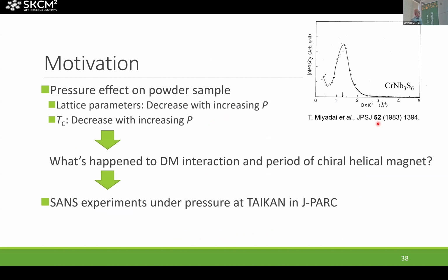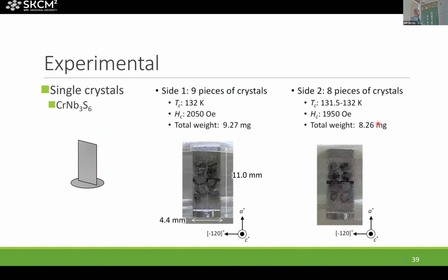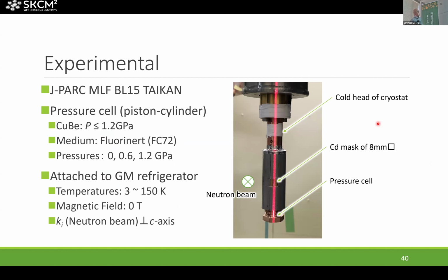So we have performed an experiment under pressure at J-PARC using a single crystal. This is the first experiment on helical magnets under high pressure. Kosaga-san prepared 17 single crystals. These crystals are all aligned in the same direction and glued on the aluminum sample cell. This sample cell is in a piston cylinder type pressure cell, which is adapted to refrigerators.